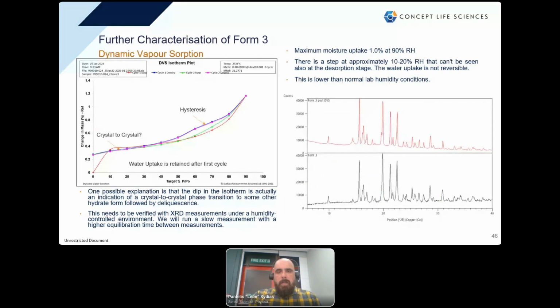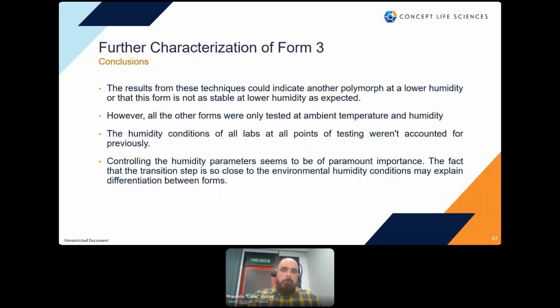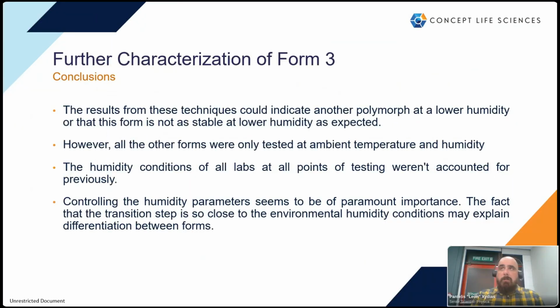We also, of course, ran some XRD after the cycling of the material, before and after. Here you can see the diffractogram. After the DVS, it corresponds to the form 3 as when you compare it with a reference diffractogram. Just some outtakes from this characterization. There's a lot to be done.